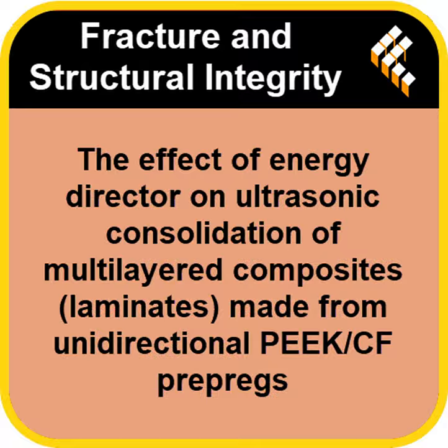But what about the internal structure? You can't see that from the outside. No, thinning doesn't tell the whole story. And the microscopic view, this is where you see the paradox in action. What did they find? Without the energy directors, the final structure was, frankly, beautiful. Uniform, robust, almost completely defect-free. Really? Yes. The original interfaces between the layers, which you still kind of see at 600 milliseconds, had completely blurred and vanished by 1200. It showed perfect, homogeneous polymer mixing.